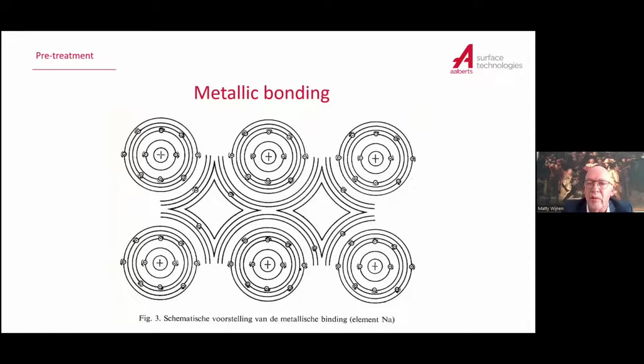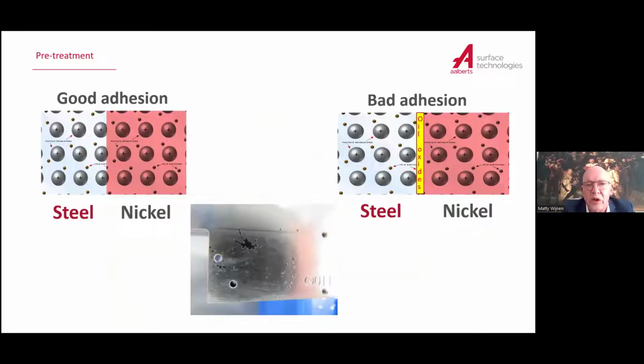If you now go to plating, you put another metal on these materials. If you want very good adhesion, you have to make sure of one thing. On the right side of the presentation, you see the atoms, and there you see those small free electrons moving around those atoms. If I put a nickel layer on them, to have a good adhesion, I have to make sure that these electrons, which are moving around my steel atoms, also make those movements around my nickel atoms. If they do that for, say, 50 or 60%, you have a perfect adhesion of your nickel layer with your steel, because you get a metal bonding.